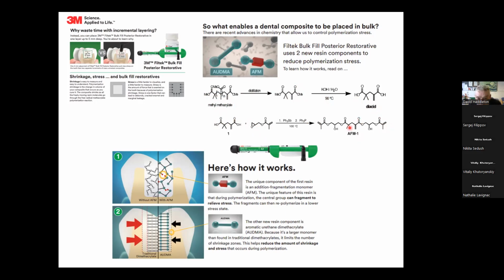And then here is the fragmentation site. That's the RAFT site. So that's a RAFT agent. That's the RAFT bit. This will then cross-link. So after the dentist has drilled out the hole in your teeth to fill it, they will do some photopolymerization. It will mainly be a bunch of different diacrylates. This dimethacrylate will cross-link, and this AFM group, while the light is on, will break and form, break and form, break and form, break and form. And so it ends up in the least stressed environment in the final product, which is your filling, really, and that will give strength to the filling.